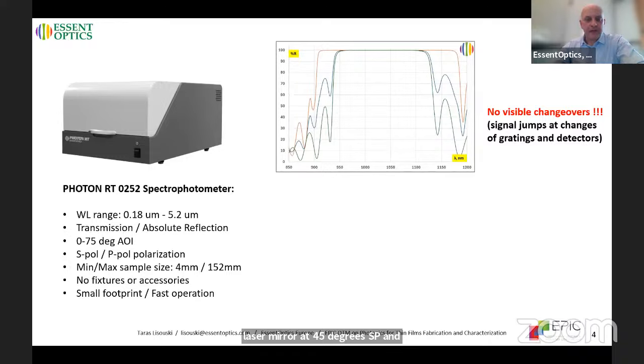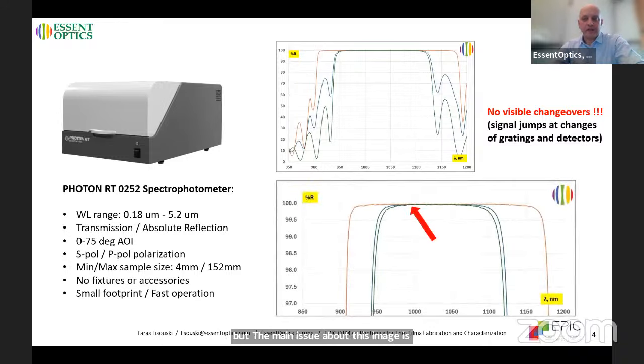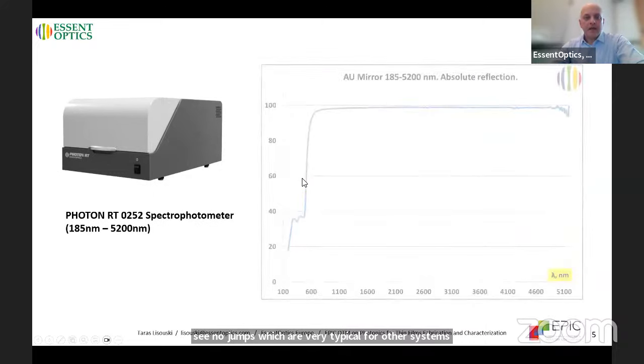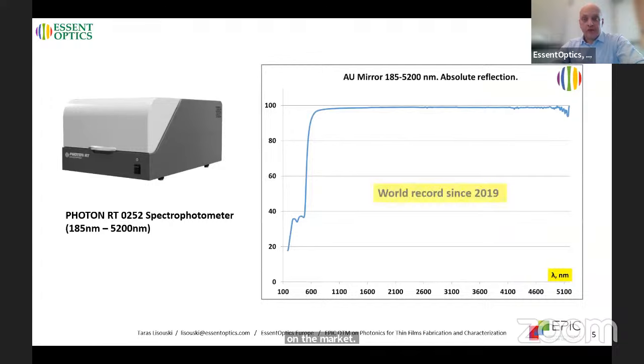But the main point about this image is that we don't have any changeovers. The arrow points to the area where we are changing gratings and detectors, and you obviously see no jumps, which are very typical for other systems on the market. We are very famous with this system for the world record broadband range. This record was set in 2019 and is still unbeaten. We do cover the range from UV to 5.2 micron in a single system, and the example shows our capability to measure a gold mirror broadband.